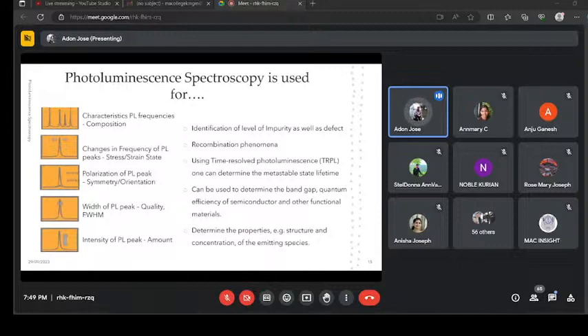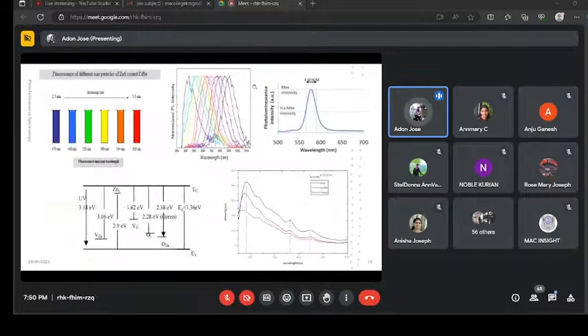Another important aspect in photoluminescence research is the width of the photoluminescence peak, because it has certain significance. This is one luminescence spectrum, and here we have marked the full width at half maximum of that particular peak. We can calculate it by taking the difference between the two extreme values of the wavelength at which the photoluminescence intensity is equal to half its maximum value.